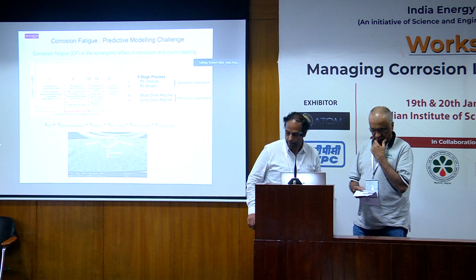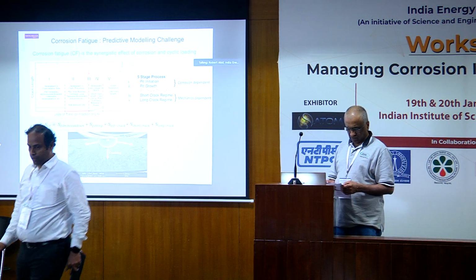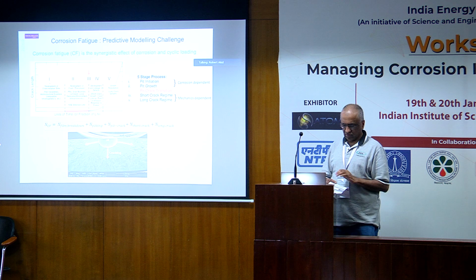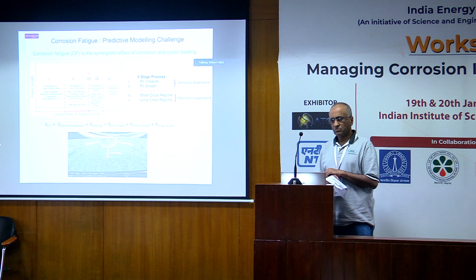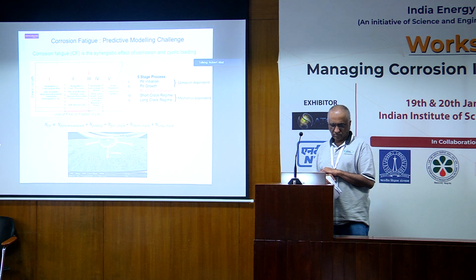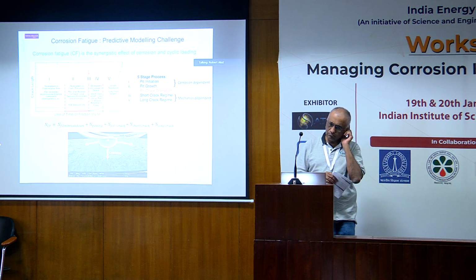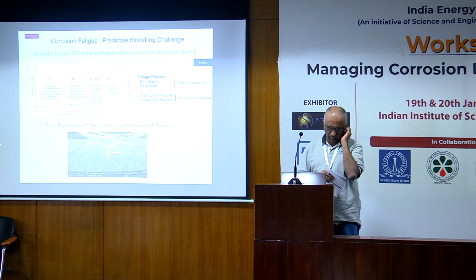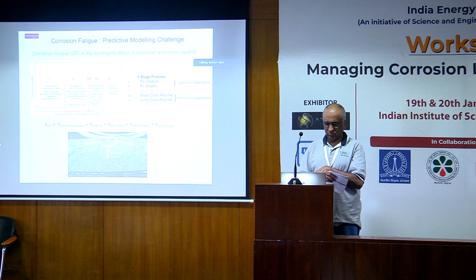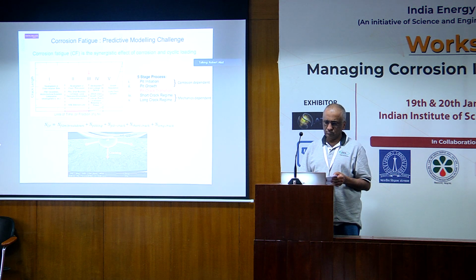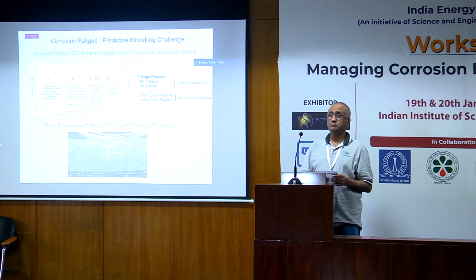Yeah. Thank you, sir. I completely agree. One of the big problems is trying to do the digital image correlation with a liquid between the surface and the camera, because you get distortions. We have done some tests whereby we have generated pits and then continued to do the fatigue cycling within the environment and looked at the lifetime.